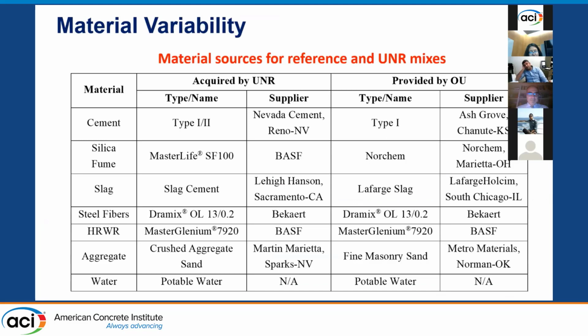So for the material variability, these are the sources that we used for our material. The University of Oklahoma, as I mentioned, are the ones who started the mix design, and they provided us already with the materials that they have used. But in the meantime, we tried to source similar materials locally here in the western part. The cement we use from a Nevada company here, and the silica fume and the slag we got from Sacramento. And the main part is the aggregate.